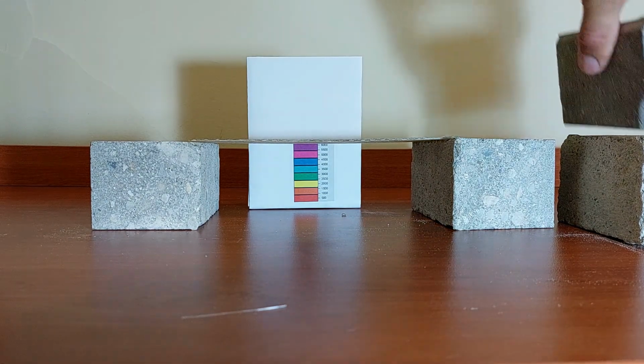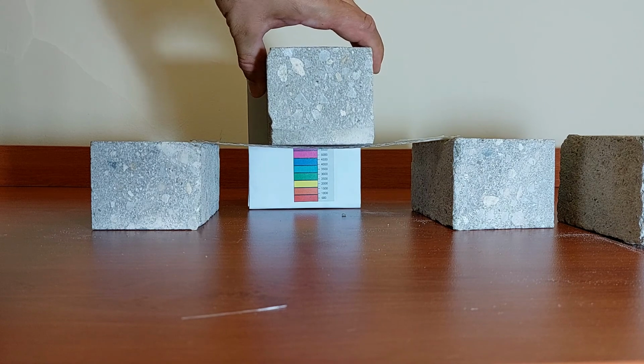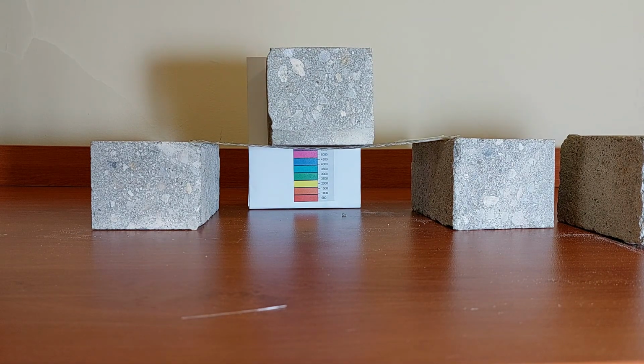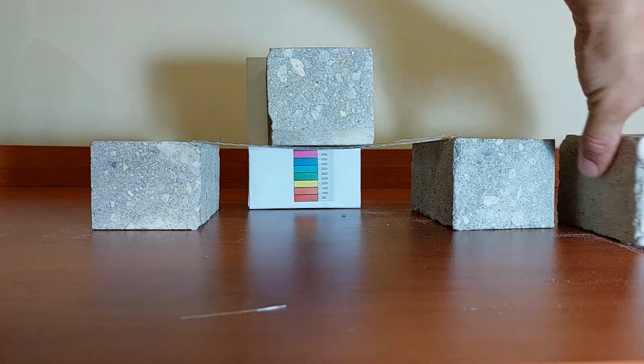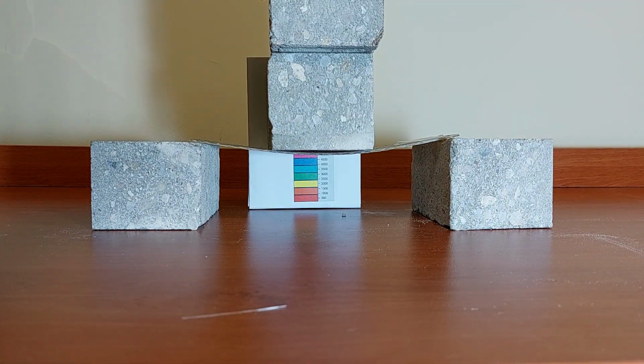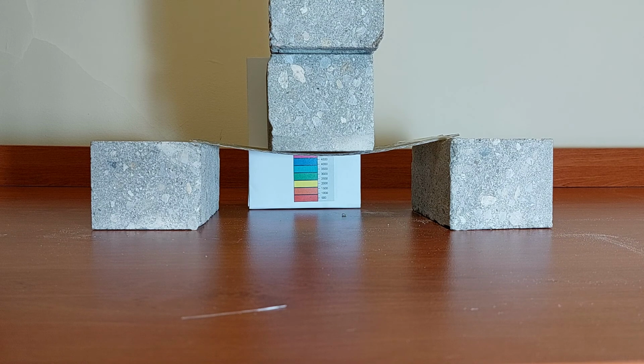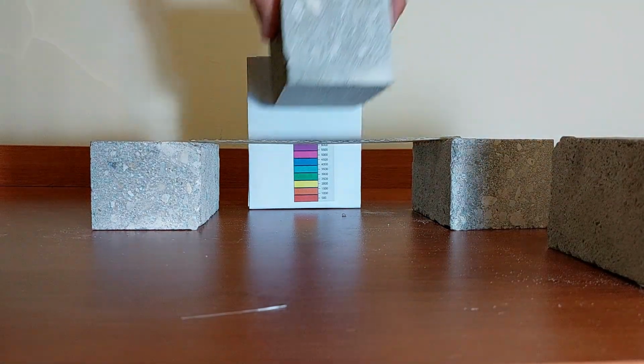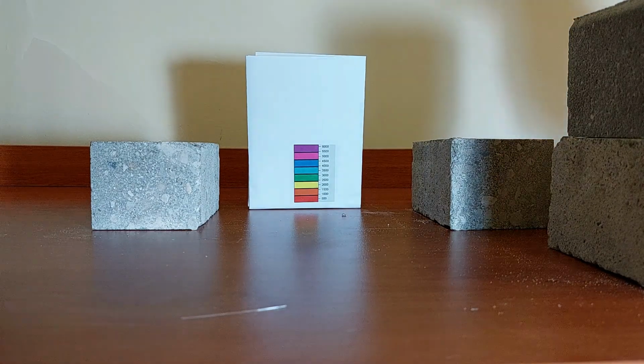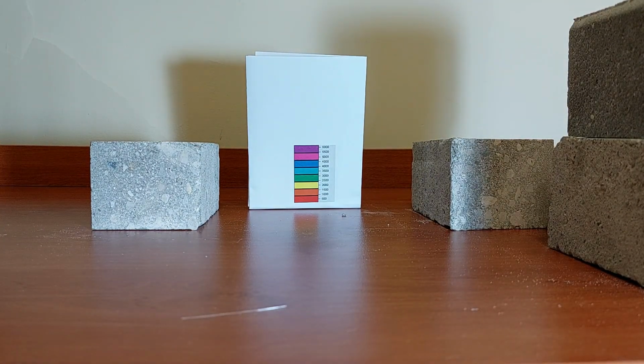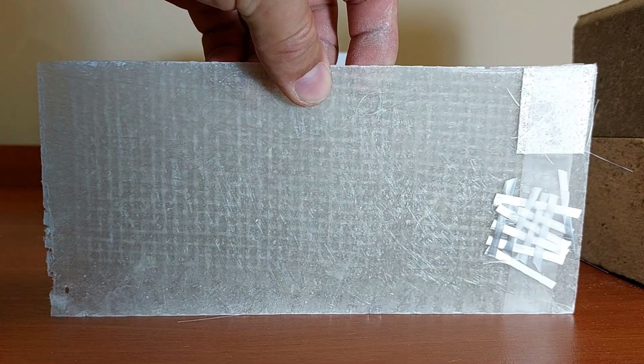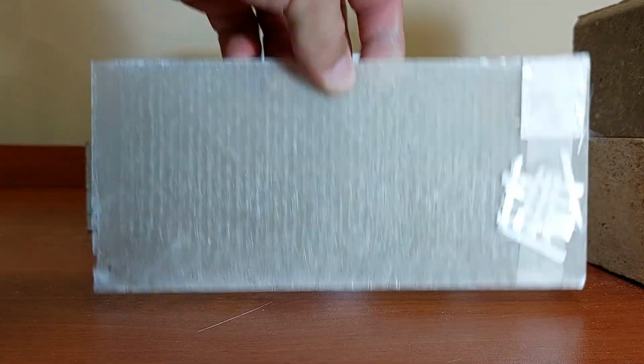And I will add the first weight. So only one color has gone down, and then I will add a second kilo to this sample. And we passed purple, we are almost to blue, so only one color and three quarters of the other one. Then I will proceed with the same test with the same fiberglass, but laminated with polyester resin instead of vinylester resin.